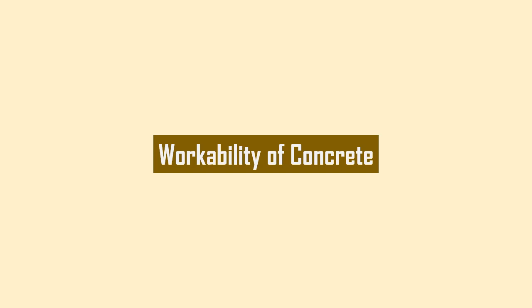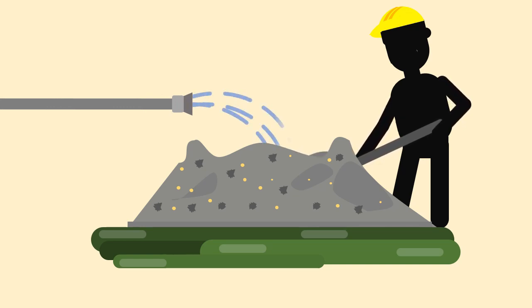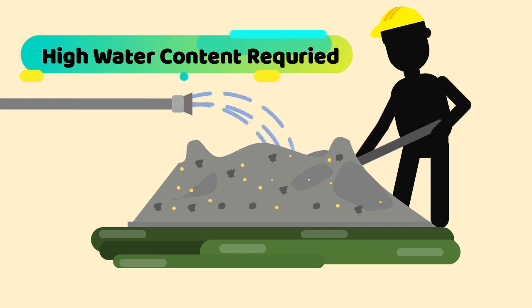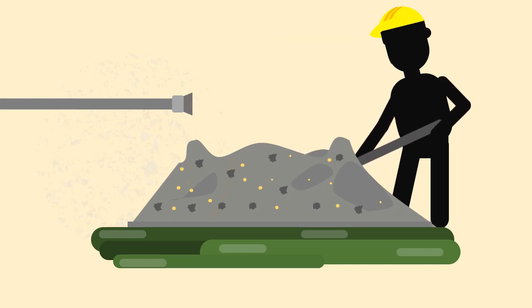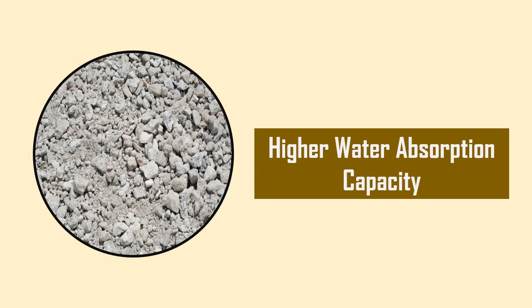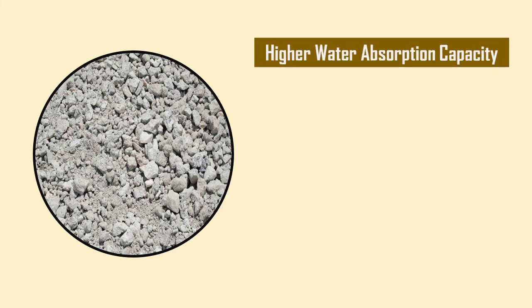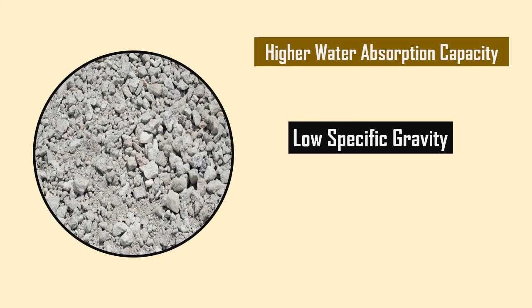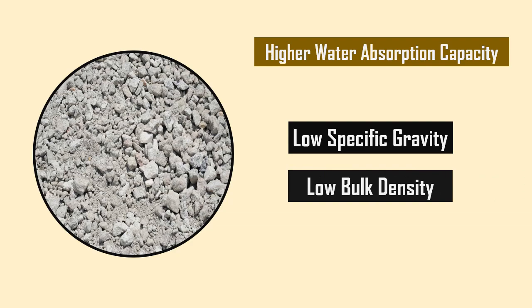Workability of concrete. To achieve the same workability in recycled aggregate concrete as in natural aggregate concrete, higher water content is required. This is due to the higher water absorption capacity of recycled aggregate. Also, due to high water absorption capacity, the specific gravity and bulk density of recycled aggregate is relatively low.